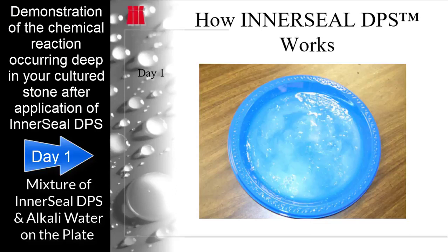This alkali water moves through the cultured stone, attacking any sealer attached to the structure. The pH of most sealers is 7.5 to 9.5, while the pH of the alkali water is around 13 to 14 — high enough to destroy any topical sealers attached to the surface.